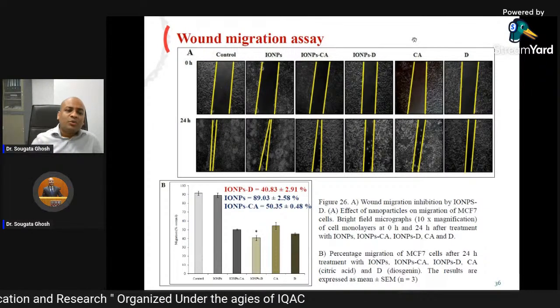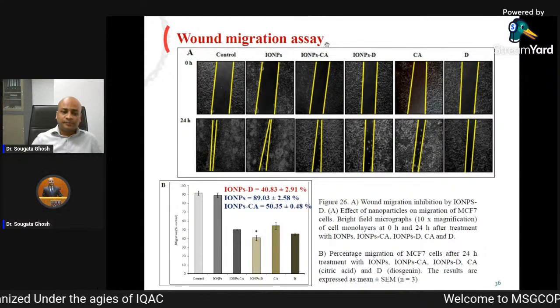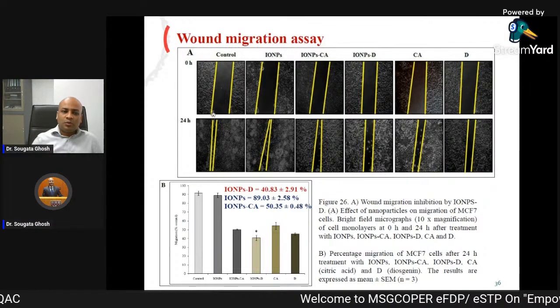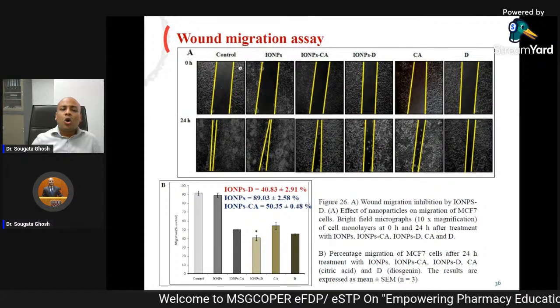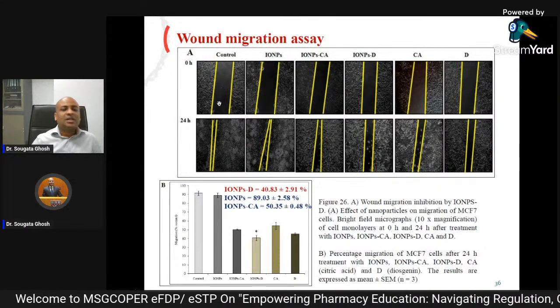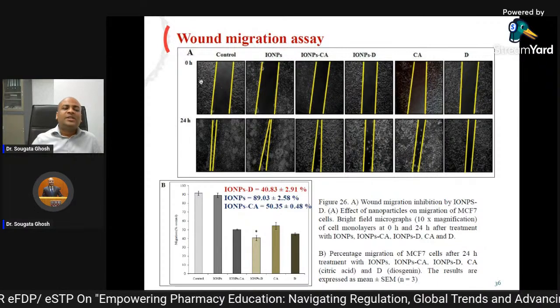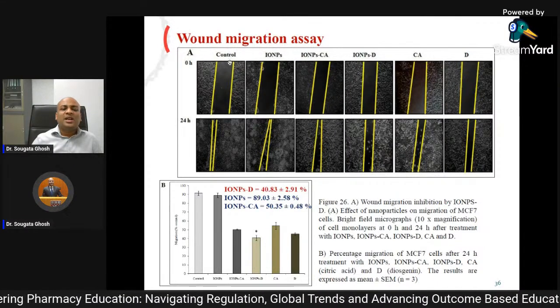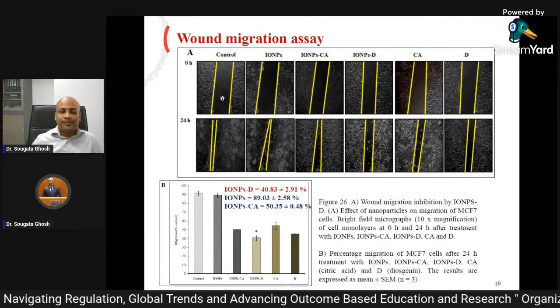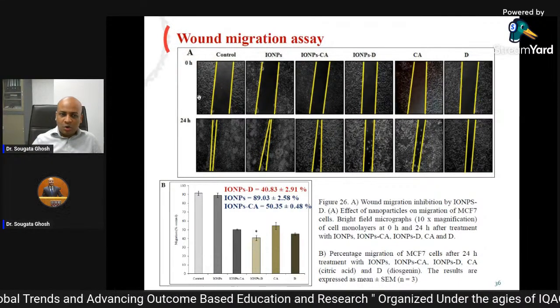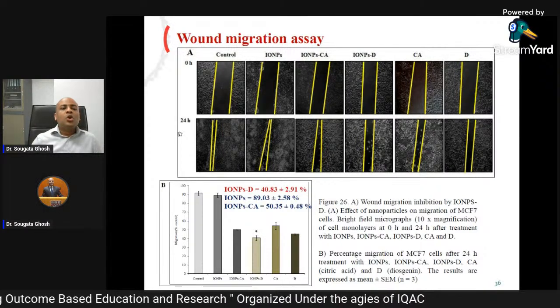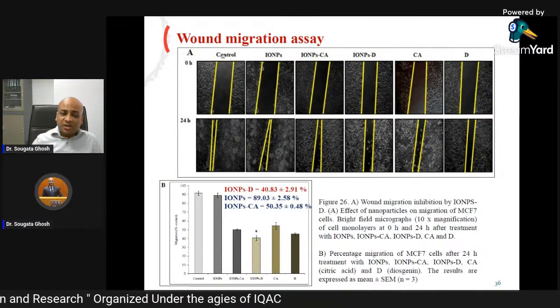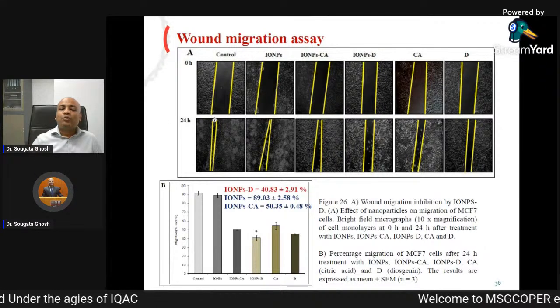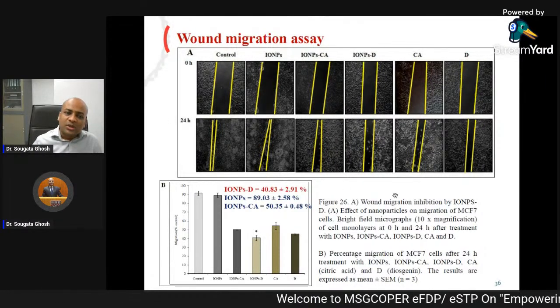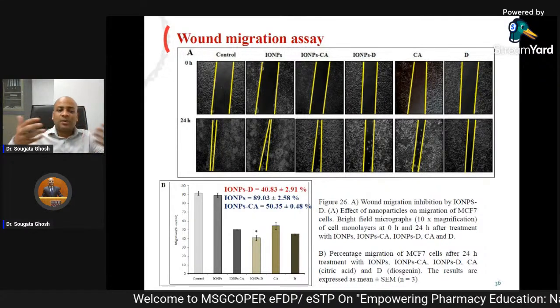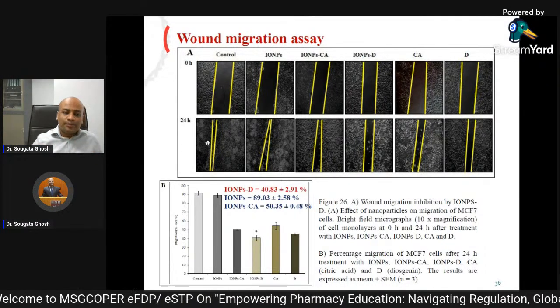So our aim was not only to inhibit cancer, but also to inhibit the migration of the cancer cell. So what we did over here is called a wound migration assay. Here you can see a control. What are we doing in the control? We are having a lawn of MCF7 breast cancer cells. And on this lawn of MCF7 breast cancer cells, we created a wound, a gap. So in the control, which was untreated, after 24 hours, the gap was almost sealed. Why was the gap sealed? Because the cells from both the sides were coming together, sealing the gap.